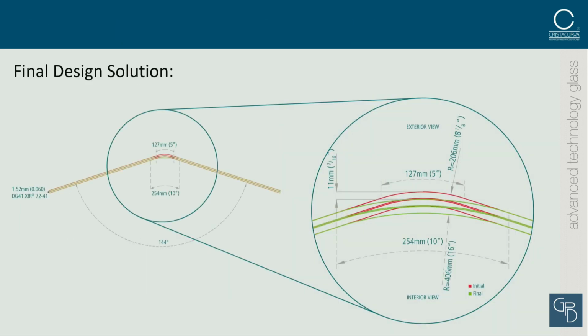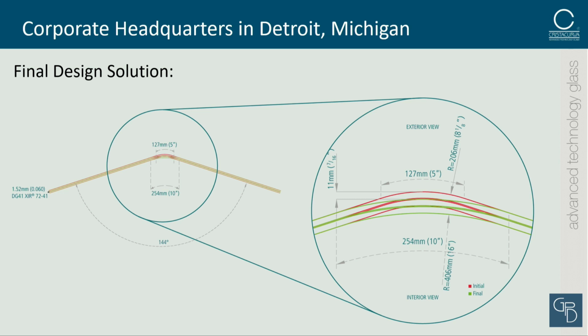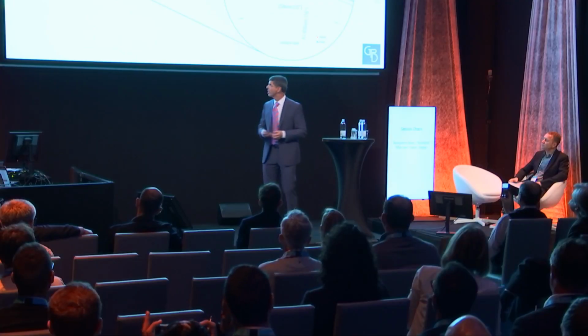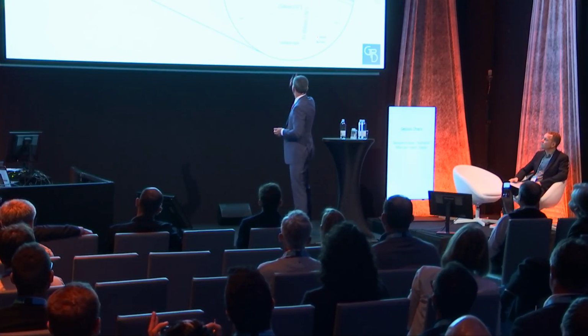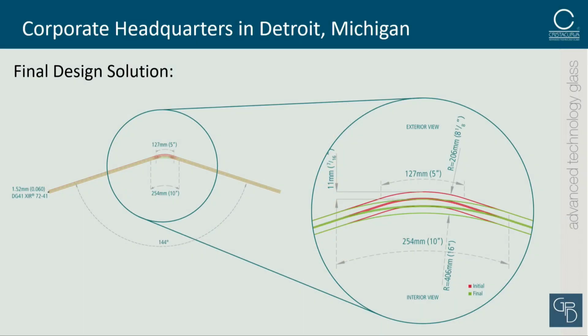So what did we do? We went back to the design team and the glazier team, and we came up with a solution, which was to increase the radius from 200 millimeters to 400 millimeters, which is twice the radius, but the shape of the glass did not change much. It was only 11 millimeters of depth difference. So the shape of the glass really stayed the same, and the coating could also stay there.